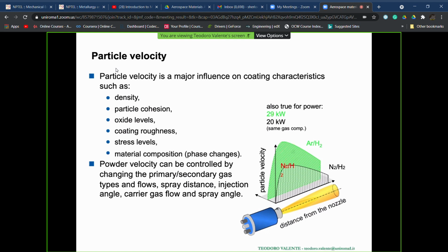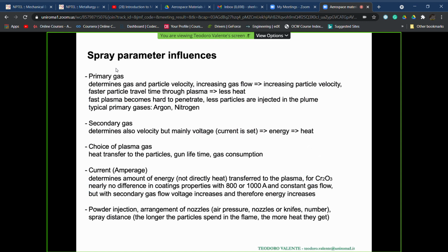and secondary plasma gas, the flow of this gas, obviously, the spray distance, the injection angle, and the carrier gas flow, as well as the spray angle. All these parameters have an influence on the particle velocity. So if you want to make a small resume of the spray parameter influences on coating qualities, we can say, according to what we have discussed, that primary gas,